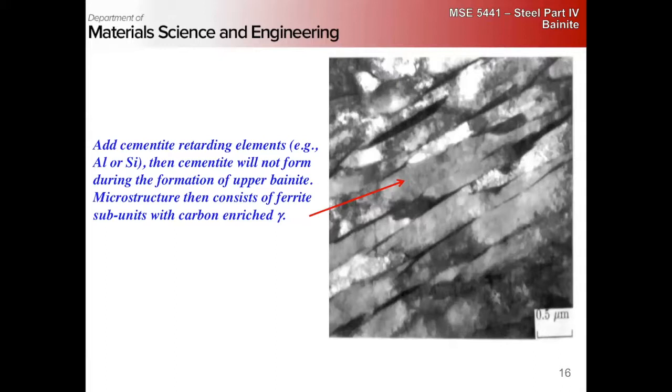Bainite happens at a high enough temperature that the carbon still has enough mobility that you don't know whether it's all happening simultaneously or what exactly the kinetics of all these little sub-processes are, because you only see it after the fact, after it's diffused out and these carbides have grown, or this carbon-rich austenite has formed, and you don't see any more of the alpha prime regions left.